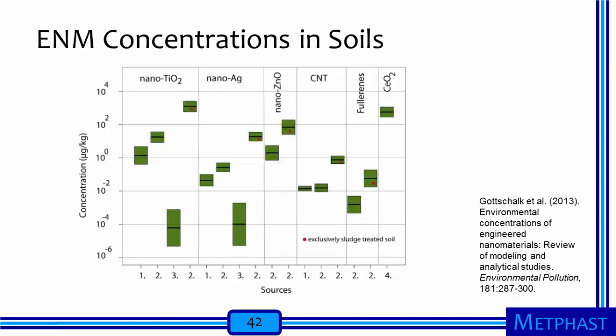Estimates for engineered nanomaterial concentrations in soils range widely, but they are mostly around 1 milligram per kilogram or lower. Unsurprisingly, soils to which biosolids from wastewater treatment plants have been applied, labeled with the red dots, are expected to have higher concentrations than soils in which nanomaterials have settled through either wet or dry deposition from the atmosphere. Interestingly, cerium oxide nanoparticles are expected to have relatively high concentrations, but this estimate was produced for soils near roadways that may experience contamination from cerium oxide additives in diesel fuel.